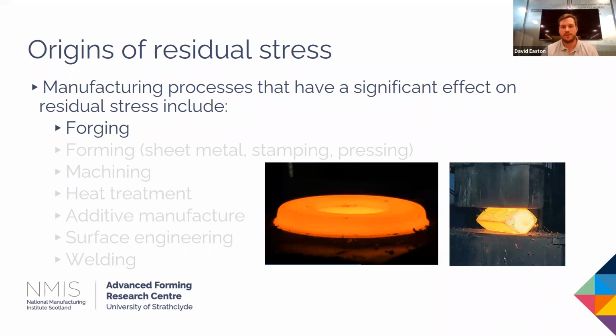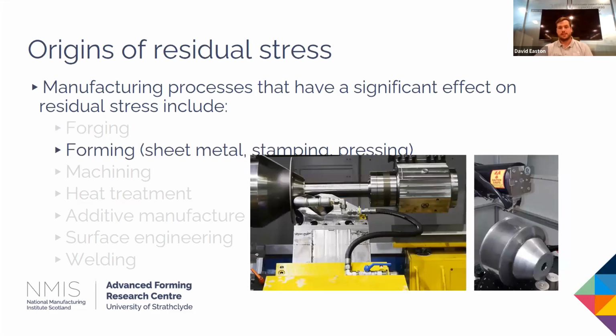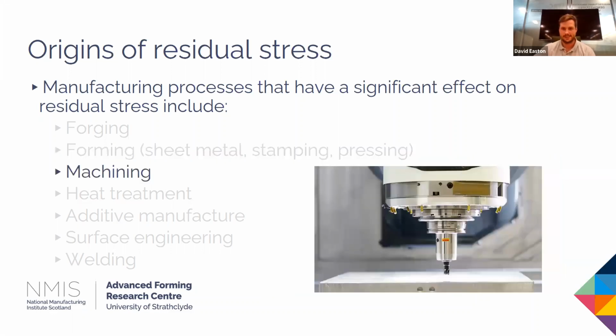To go briefly through some of the common sources of residual stress that we see here at the AFRC or that you're likely to see in manufacturing around the country. Forging, so whether it's open die or closed die forging, you've got severe deformation being imparted, you've got high temperatures, you've got temperature gradients, all of these result in stresses developing. Similarly with forming, cold forming or hot forming involves severe plastic deformation, again high levels of deformation and strain being imparted, resulting in high levels of residual stress.